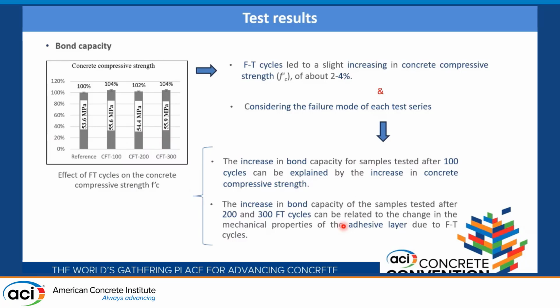This graph on the left shows that freeze-thaw cycles led to a slight increase in concrete compressive strength of about 2 to 4%. And considering what we saw about the failure modes of each test series, it can be stated that the increase in bond capacity of samples tested after 100 cycles can be explained by the increase in concrete compressive strength, and the increase in bond capacity of the samples tested after 200 and 300 freeze-thaw cycles can be related to the change in the mechanical properties of the adhesive layer due to freeze-thaw cycles.